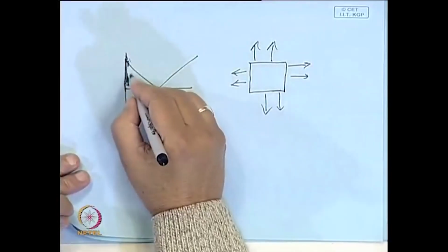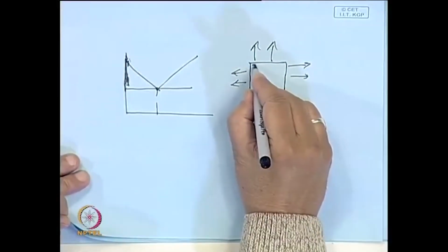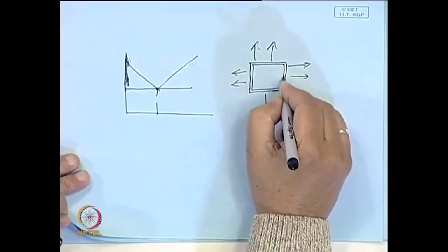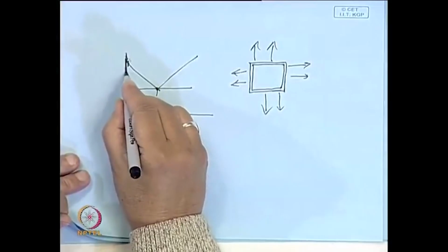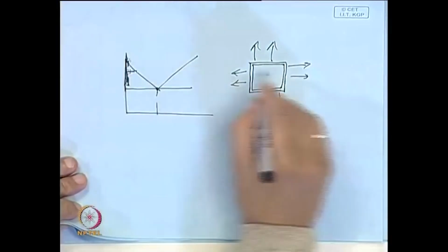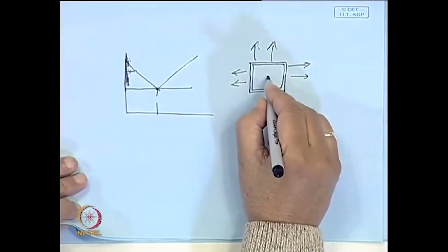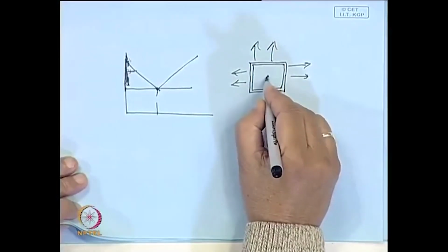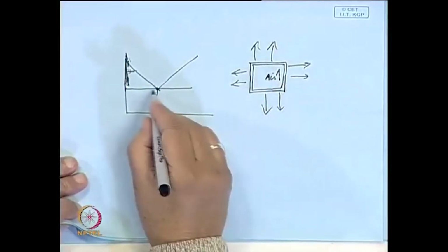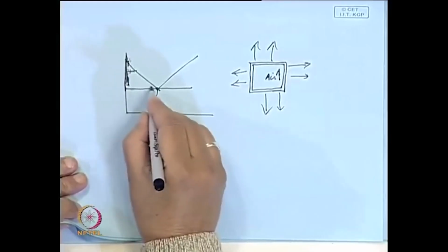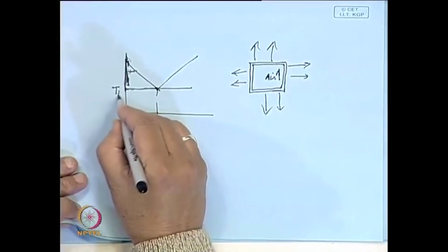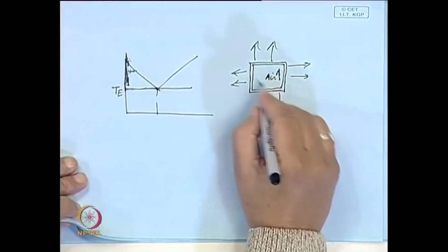In that case, the first layer that ice will form is planar, and this will go on rejecting the air to the water. So this becomes richer in air, the air concentration increases here, and ultimately when it reaches this particular temperature, that is the eutectic temperature, then both